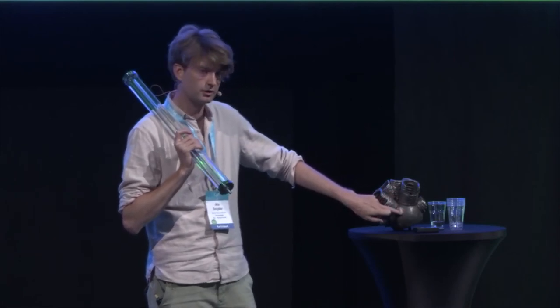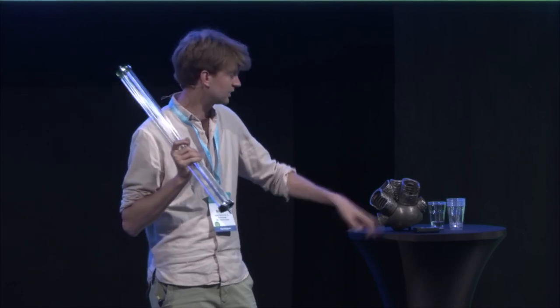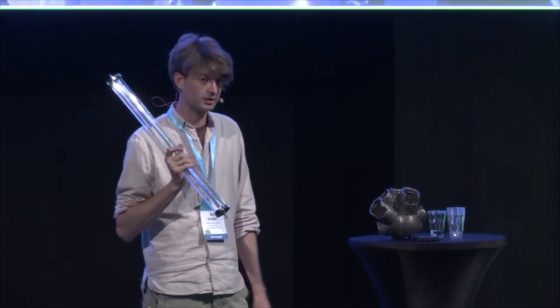Question: How are the nodes connected to the steel ball — you just printed on the steel? How is the 3D printed part connected to the cast steel? This was a little bit of trial and error, because the 3D printing company needed to know what kind of steel the spheres were. We went back to Octatube and asked what steel it was, and they didn't know — space frames built in the 90s from cast steel nodes ordered from India. We were unable to find out the steel quality, so Ramlab had to do trial and error with temperature settings and printing speed to make sure the printed part adheres nicely to the cast steel sphere. At some point they got it right, and with those settings the rest of the nodes were made.